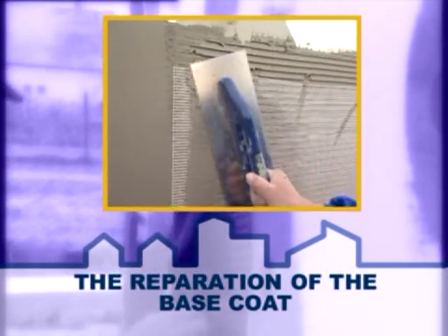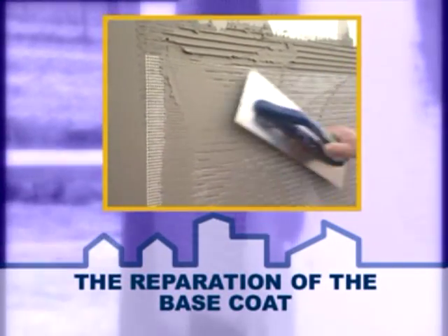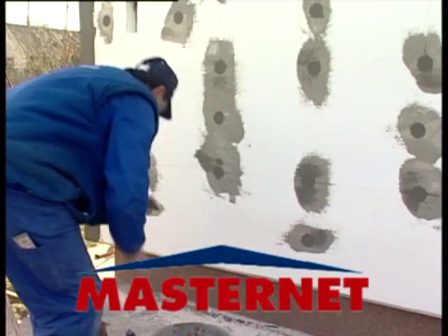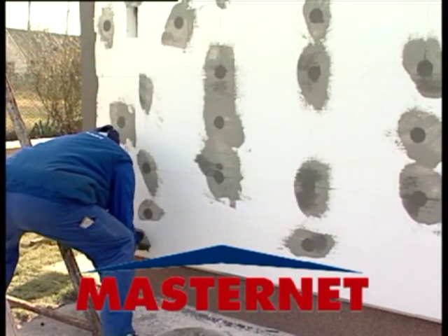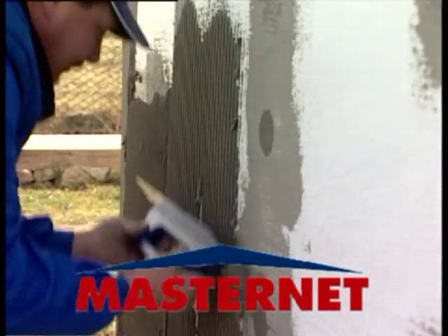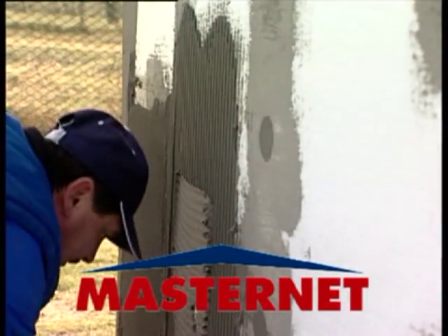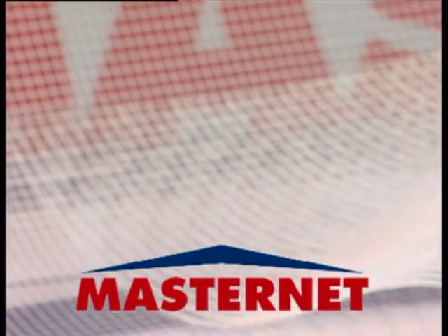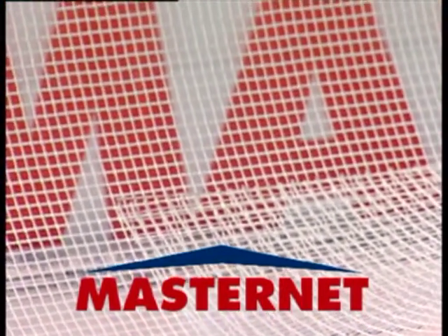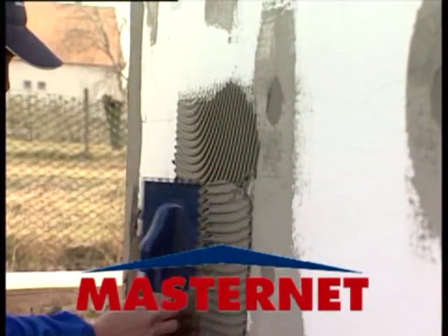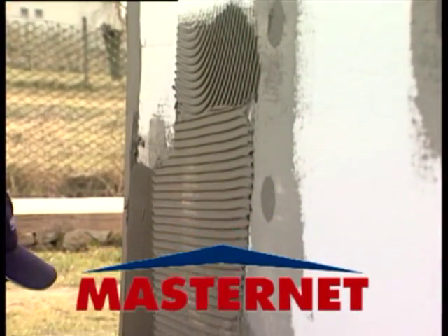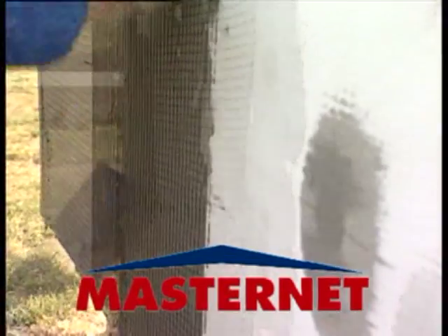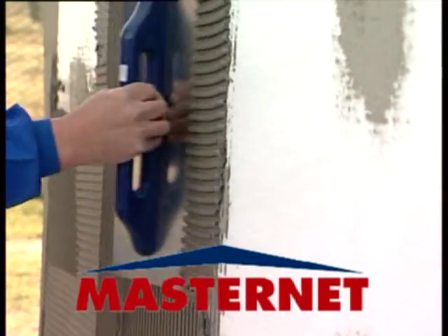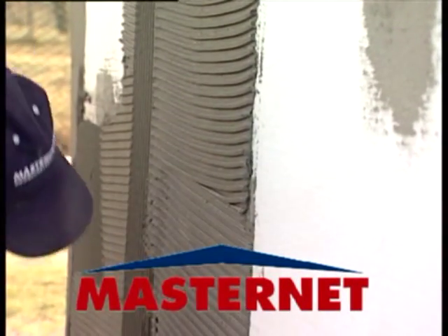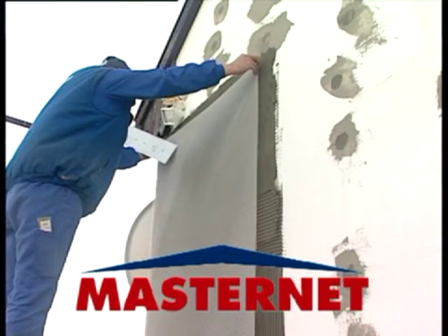The preparation of the base coat. The base coat ensures the adequate hardness of the thermal insulation system. Embed fiberglass mesh with a unit weight of at least 145 grams per square meter into a minimum 3 mm thick adhesive layer above the EPS boards. The prescribed thickness must be ensured along the entire surface. This can be achieved by the application of the adhesive with an at least 8 mm notch-sized notch trowel.